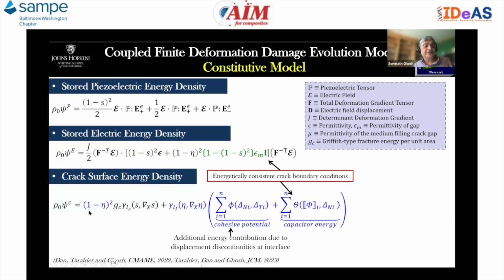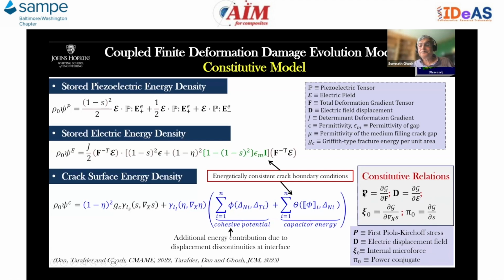and this corresponds to the crack surface energy density. The first term here that you see corresponds to the matrix energy density, and the last part corresponds to the interfacial energy density. And here with the identification of eta corresponding to the interface, we can introduce the cohesive potential and the capacitor energy because of the electrical fields into this crack energy. You can see some of our publications on this for more details.